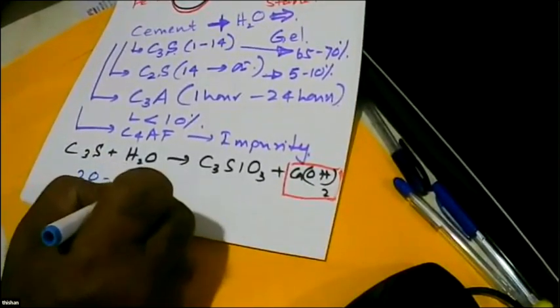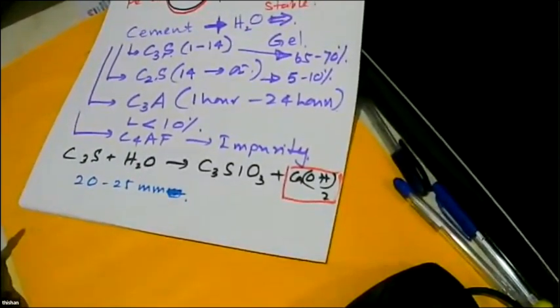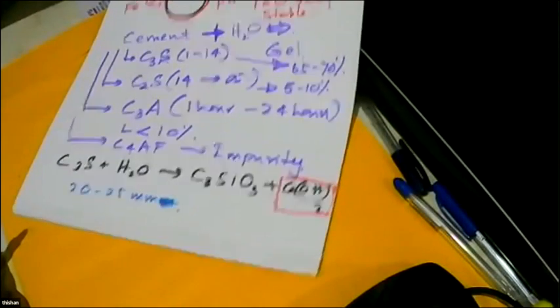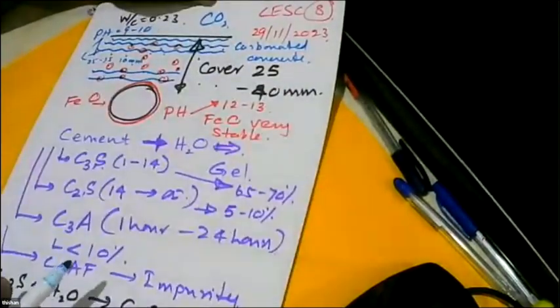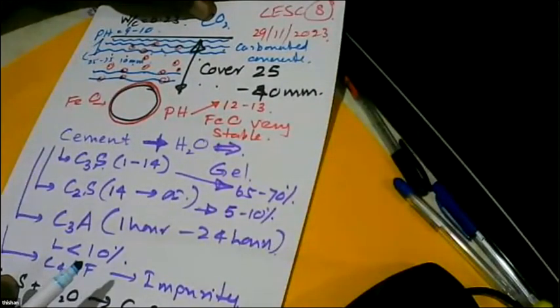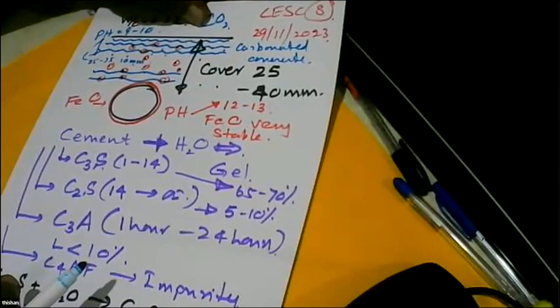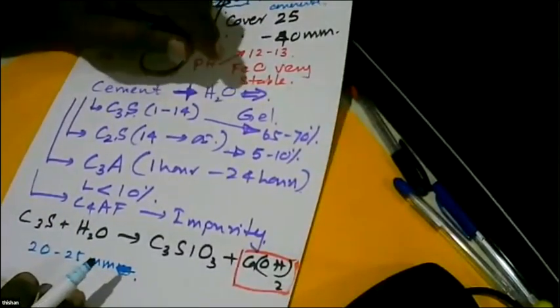So, what is the minimum cover that we need? We need a minimum cover of 20 to 25 millimeters if you are expecting a reasonable duration without any trouble in a concrete structure. That doesn't mean that the moment it comes here, it is going to corrode and the structure is going to collapse. No, it's not. If you are protecting the structure, oxygen content is low, and the oxygen cannot come into contact with the reinforcement. Water is not available. It's all in dry condition. Even a carbonated structure can last many years, but you're asking for trouble when the carbonation has reached the steel. So you have to take a lot of precautions when you are maintaining. Before that, even if you don't do anything, concrete will still protect the steel. No corrosion. So that's what you have to keep in mind.